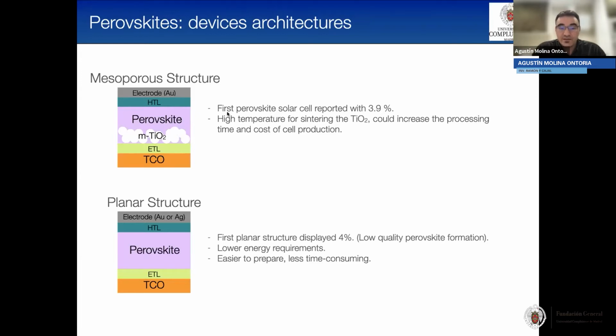These kinds of devices were the first ones reported, with 3.9%. And right now, the problem with this is the high temperature that we need to sinter the titanium oxide, which is around 500 degrees. That increases the processing time and the cost of the cell production. On the other hand, we have planar structures in which we get rid of the mesoporous titanium oxide, following more or less the same structure, and they are showing very nice efficiencies right now, even comparable or higher than the mesoporous structure.